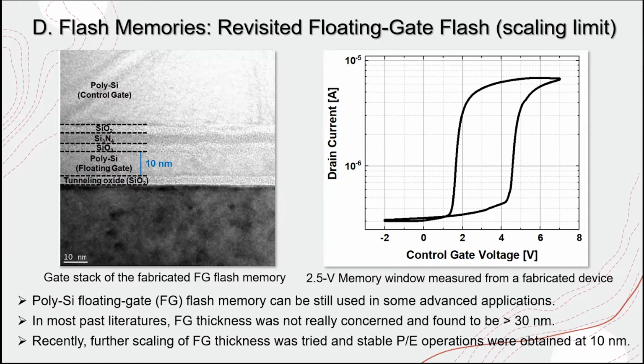But I was questioning how thin it can be deposited. So I tried with 10 nanometers, and although the memory window was a little bit shrunken compared with those found in past literature, at least we can expect more than twofold. Actually, a 2.5 V memory window can be expected from that highly scaled floating gate thickness. That is comparable to the nitride layer thickness in the CTF memory. So in some applications, the floating gate flash memory can be recalled again, because it also has silicon compatibility and can be applied to embedded flash memory technology in the processor.